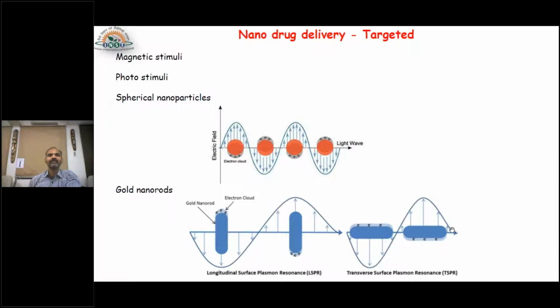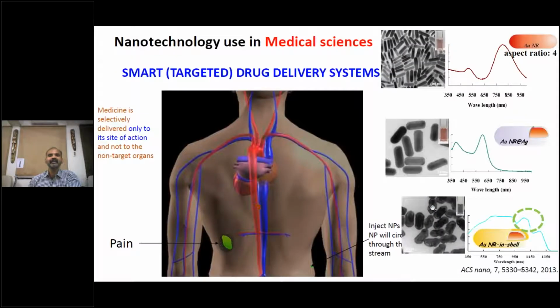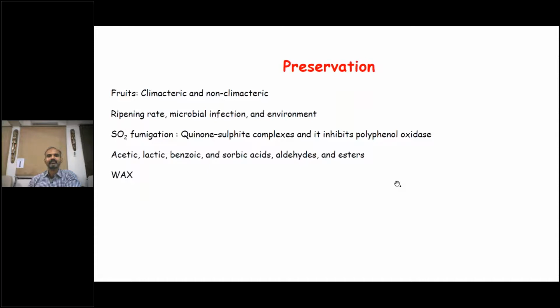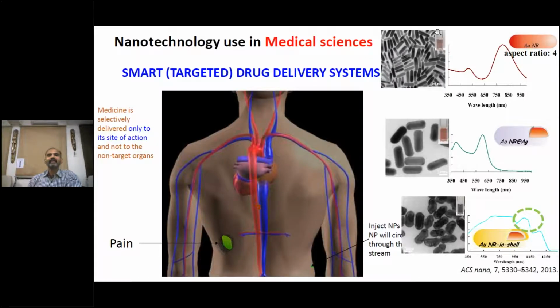This is what I was working on, the targeted therapy. Say here we prepared the particle, and then we want to use it. This was already done. As you can see, with an aspect ratio of 4, with a longitudinal length of 40 nanometers and a transverse length of 10 nanometers, that is called an aspect ratio of 40 by 10. That gives an NIR absorbance at 808 and also a transverse absorbance at 520 nanometers. But here again, the depth of penetration may not be very deep. We want to go very deep inside.